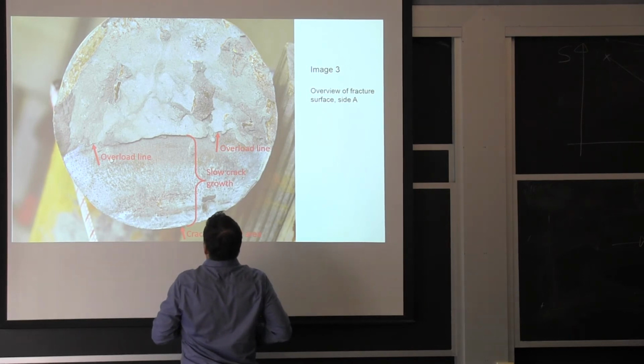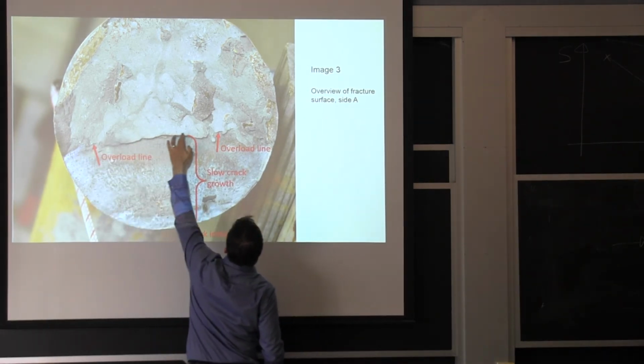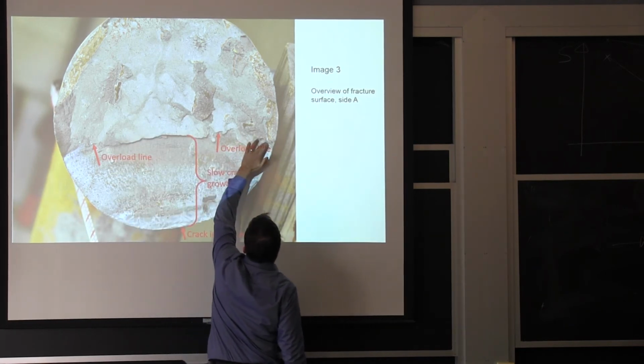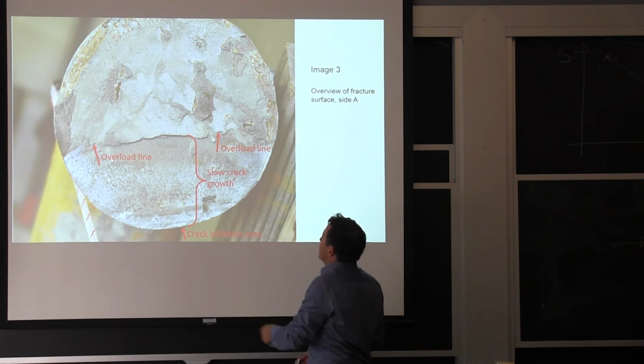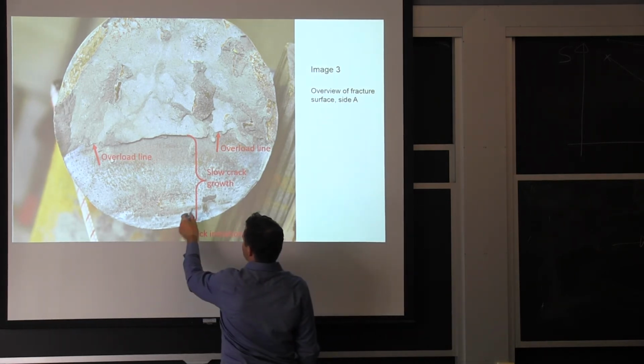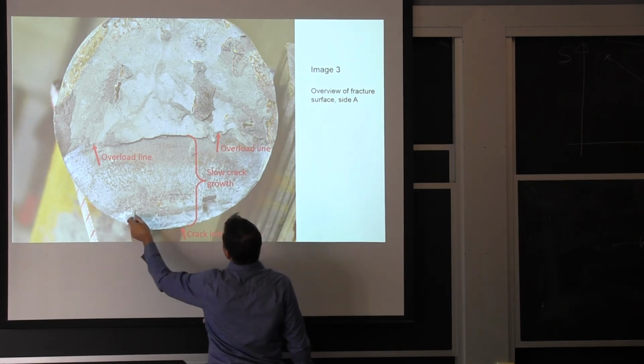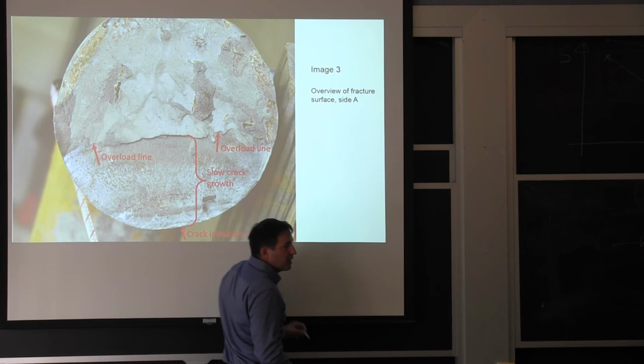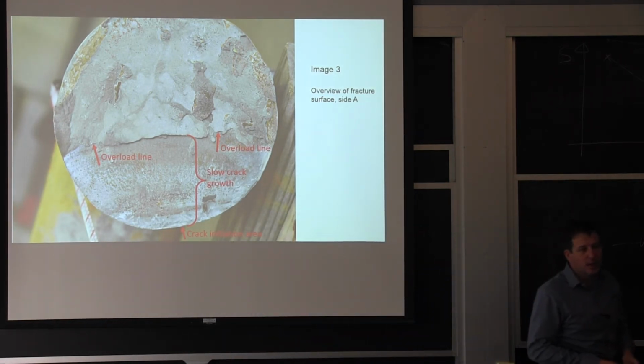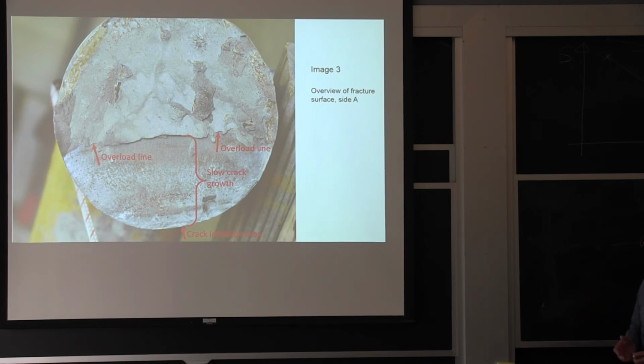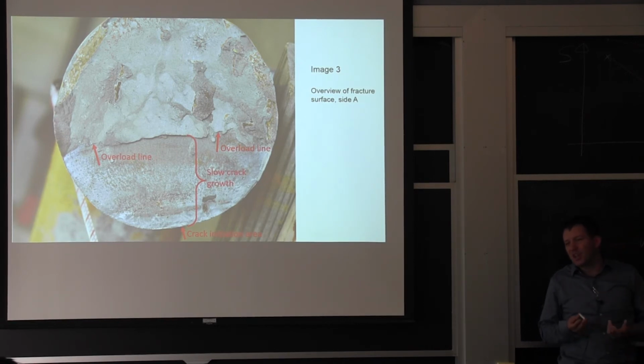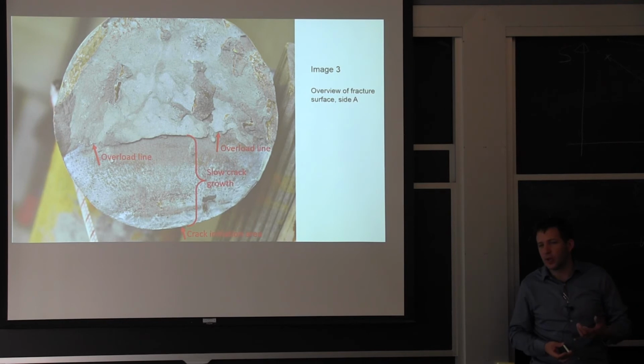There are a number of reasons why we know that this is the size of the crack at this time and depth. It was the final point before everything let go. One of the first indicators, you see a number of beach marks. The image is not perfectly clear here, but you can see distinctly about 7 or 8 of them very close to the overload line. So that tells you how far the crack went before the final fracture. The main consequence of this is we know it wasn't really an overload, because if the chain was able to sustain the buoyancy force when it had a crack about 40% through the cross section, it means you didn't have that much load. Otherwise, it would have broken much sooner than that.